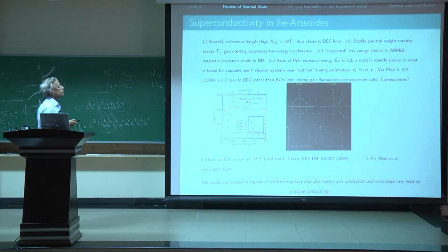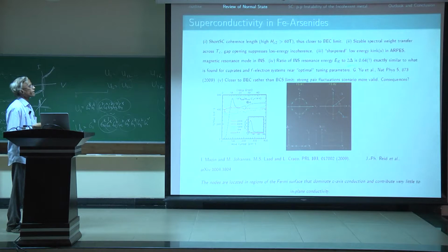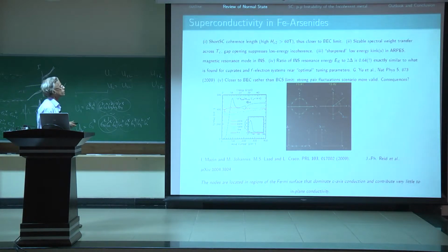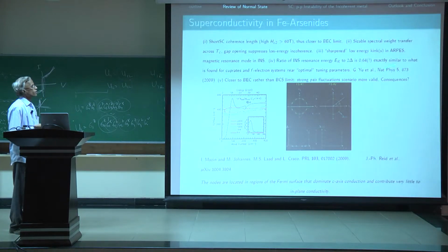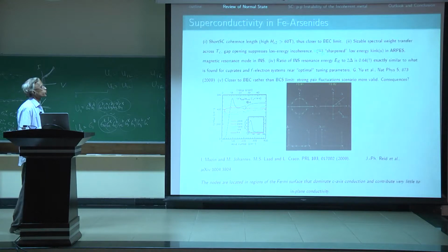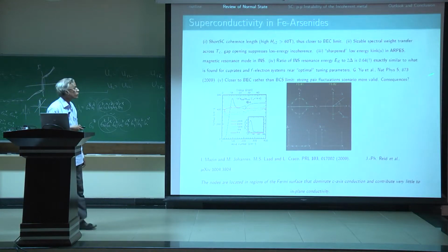In particular, there are sharpened low-energy kinks which are orbital dependent in angle-resolved photoemission. The resonance mode in INS, whose ratio to the gap function is basically exactly similar to what is found for cuprates and F-electron systems near optimal doping.